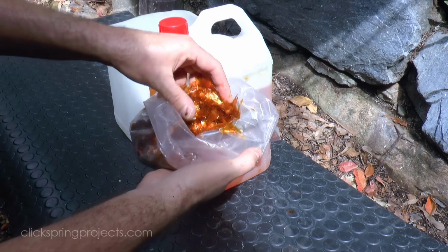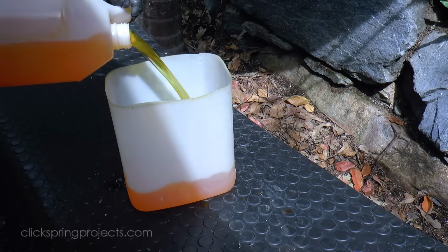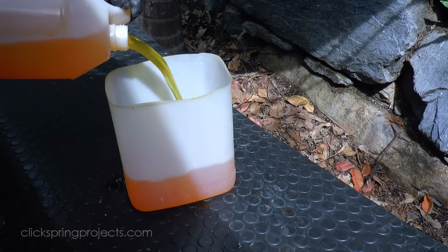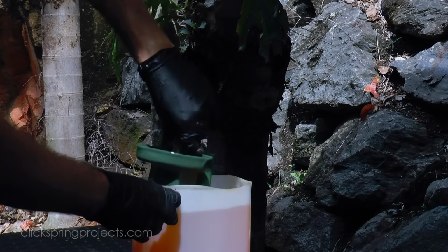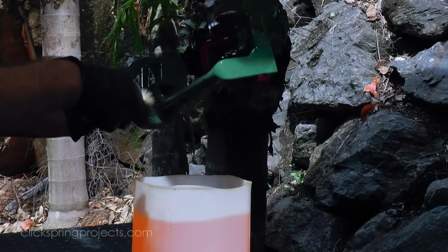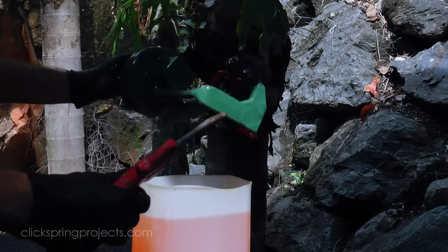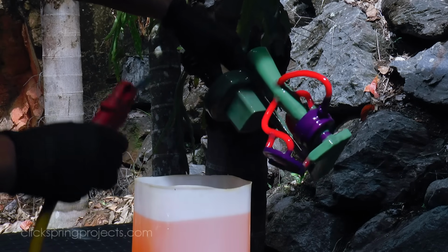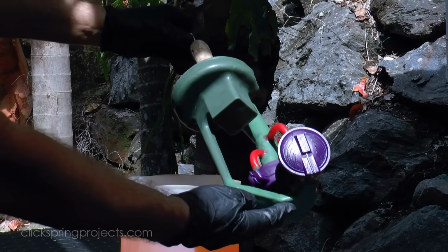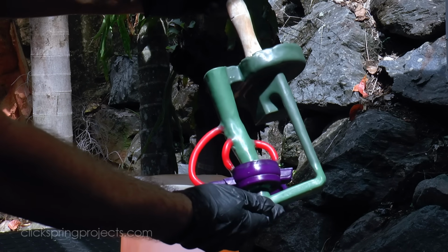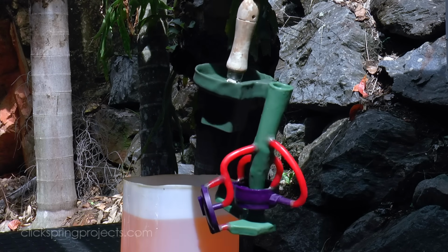This coarser material functions as a filler to bulk up the mould for greater structural strength and to give it additional thermal mass. Now with resin-printed models, a wetting agent is often required to ensure the first coat of slurry fully adheres to the pattern. I'm using shellac flakes, something like 200 grams, dissolved in 5 litres of denatured alcohol. Once dry, the pattern is ready for the first investment cycle.